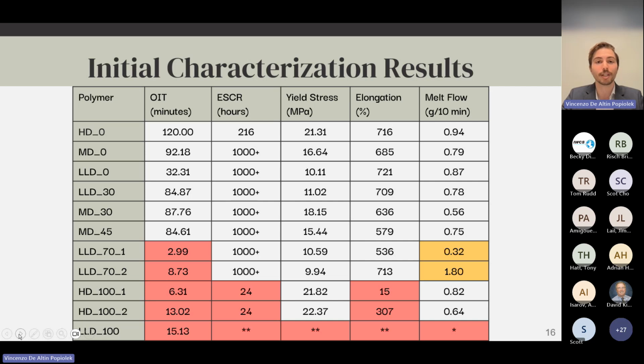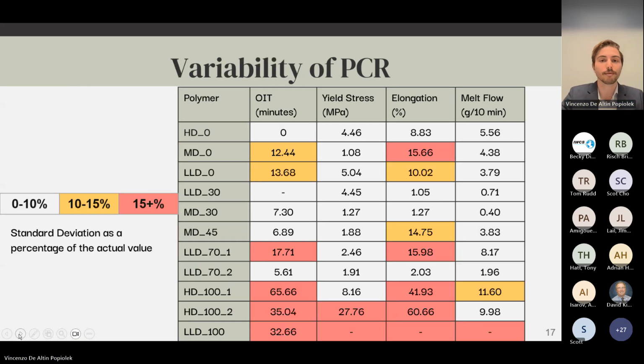For melt flow indexing, there is no industry standard. However, our target was for our final sustainable blends to have a melt flow similar to the virgin polymers currently used by the Prysmian group to make for easier processing. As such, the linear low density polymers were flagged as they were furthest removed from those virgin polymers, while the high density polymers were deemed close enough to be an easy transition.